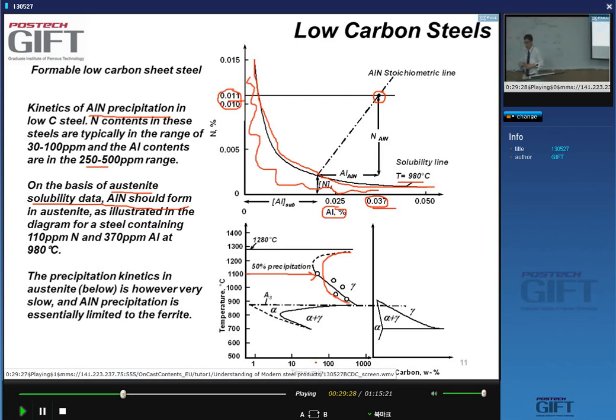However, we know that in the run-out table, the austenite transforms to ferrite, and the solubility of aluminum nitride is even lower in the ferrite. In this case, we do get very much faster precipitation kinetics. You can see here a very sharp nose, and it takes a much shorter time to form